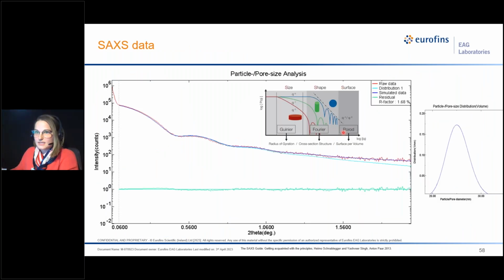So we have a SAXS example. These are iron oxide particles in toluene, and this is a small graphic of what you can get from SAXS. You get size, shape, and surface. And again, this is a simulation-based data collection where a computer program simulates a pattern that matches the experimental, which then gives you information like your particle or pore size, which you can then use to create graphs like this, giving you the distribution of those particles or pores and things like that.